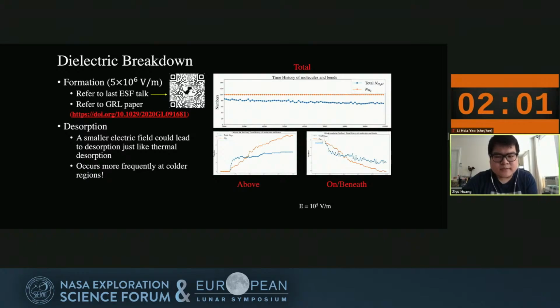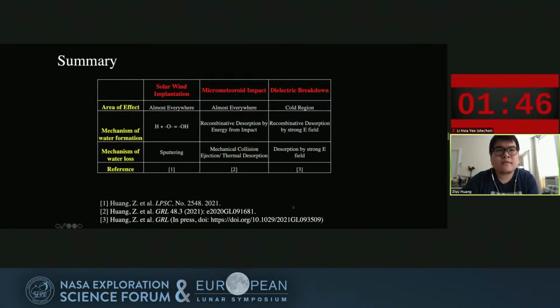Originally we thought that cold regions, especially PSRs, are very quiet and everything stays as it is. But the deep dielectric charging theory shows that there could be some loss mechanism just because the surface is too cold. And here we put a table as a summary listing each space weathering process and the mechanism of water formation and loss, and also the area effect.